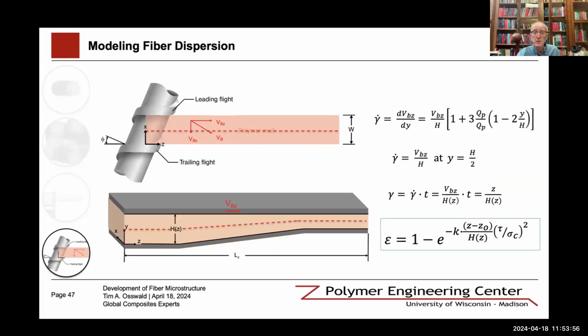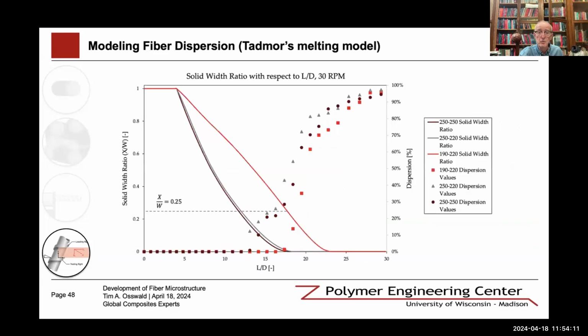We used the melting model by Tadmor and Klein, and we applied the Manas-Zloczower dispersion model, and we were able then to compare the model to the experiments. And one of the things that we found is that dispersion doesn't start until a melting of about 25%. So where the solid bed is about 25% of the width of the channel, and that's where basically we know that dispersion begins.